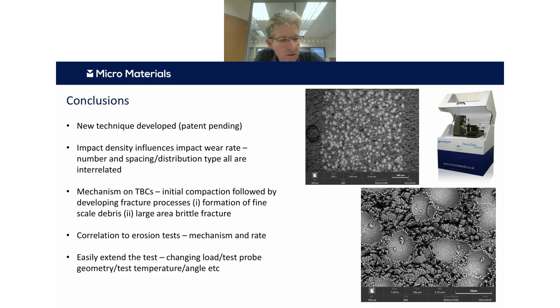It was nice that we're able to show quite nice correlation between the mechanism and the rate of the actual erosion tests. And I should say, although I've presented some results, it's also very easy to extend the tests by changing the load or test probe geometry, changing impact angle, and indeed changing test temperature as well. So it's a very flexible test technique. It's all possible within our impact module in the NanoTest Vantage system, shown there on the right.